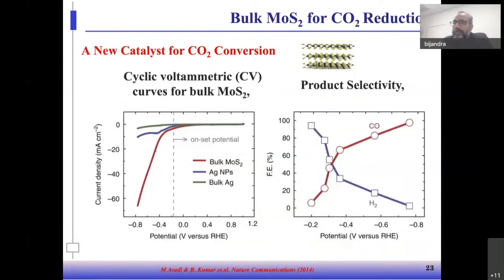We tried to investigate the CO2 electrochemical properties of this TMDC catalyst. In the first work that we did, we used bulk MoS2 and tested it for CO2 electrochemical conversion. What we observed is that bulk MoS2 has at least 100 times higher current density compared to bulk Ag, and at least 6 to 7 times higher current density compared to silver nanoparticles. And we are able to produce a tunable mixture of carbon monoxide and hydrogen depending on the potential. This mixture of carbon monoxide and hydrogen is called syngas. And depending on the ratio of carbon monoxide and hydrogen, the syngas can be used for different applications.